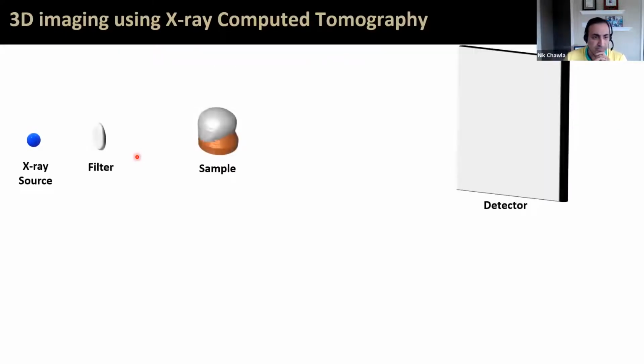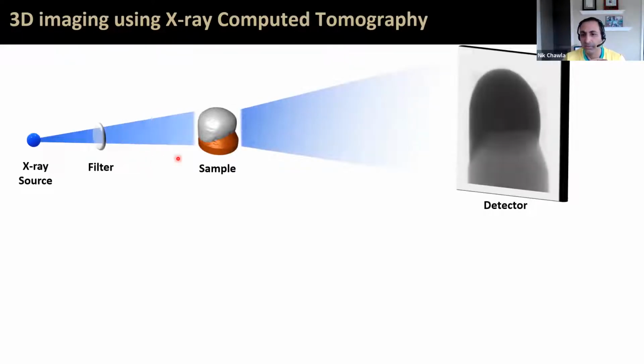All right. So how does the technique work? Well, we start with the X-ray source, and your sample is sitting here. And typically that X-ray gets filtered to some degree depending upon what range of the X-ray energies we want, because in the lab this is a polychromatic beam, so multiple energies. And so we shoot the X-rays through the sample and we get a projection on the screen here.